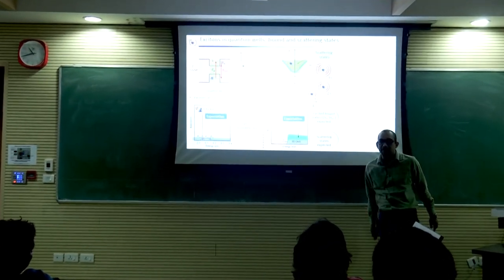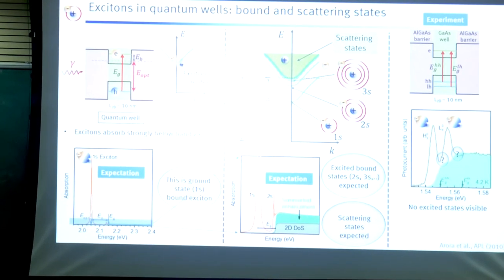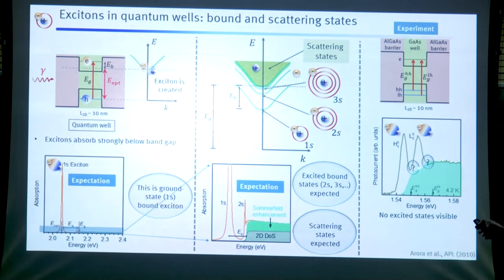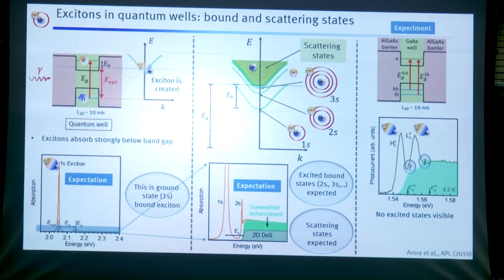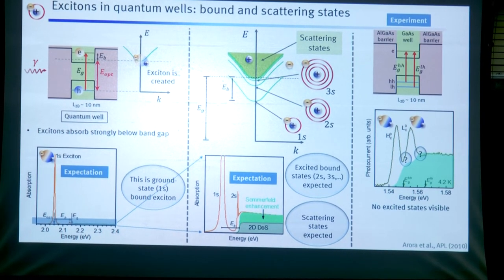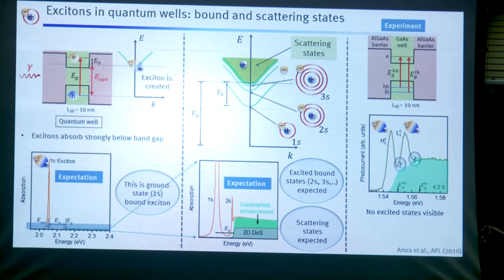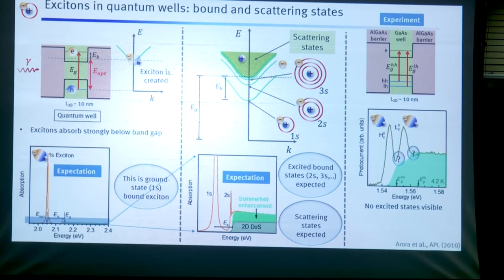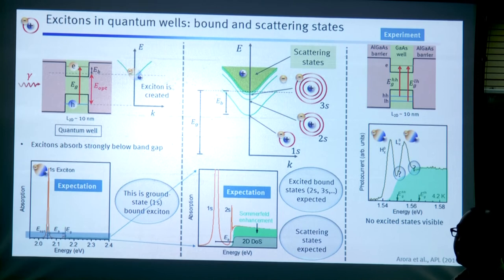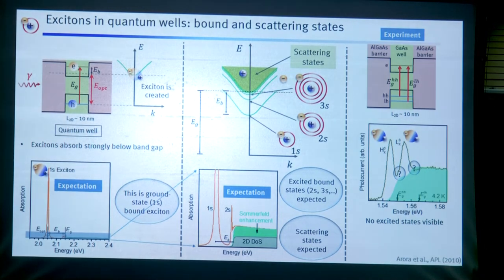So if we want to see these 2S states and 3S states and so on, what do we do? The point is these are very close to this band edge, 2S, 3S and 4S. So you have to somehow separate them. In real experiments, you see these excitonic transitions, which are only 1S states. To see the 2S states or 3S states, they are very close to a band gap, so they are normally not visible. Also, their intensity is much lesser. So they are just merged with the band gap.